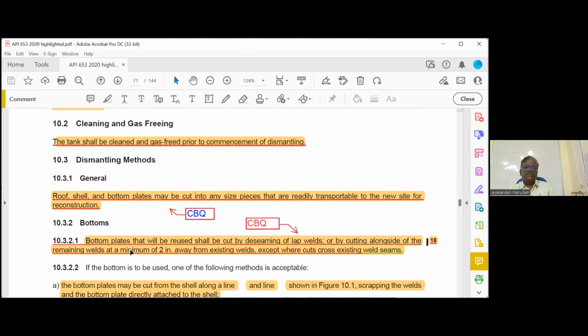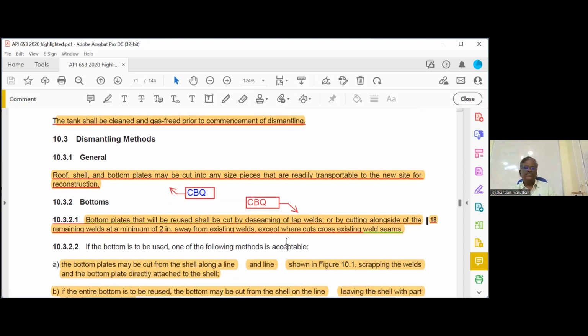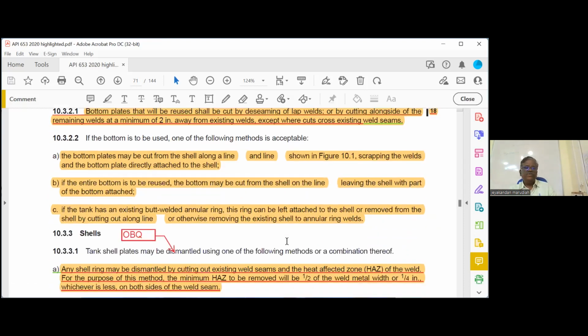Then this is an important closed book question. Bottom plates that will be reused shall be cut by deseaming the lap welds or by cutting alongside the remaining welds, remaining minimum 2 inch away from the existing welds. So either you have to deseam it. Deseaming means removing the weld and plates, taking the plates away, or it should be 2 inch away from the existing weld. Then these are not important.